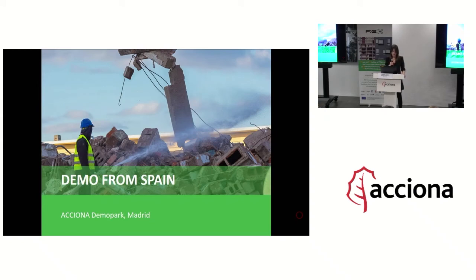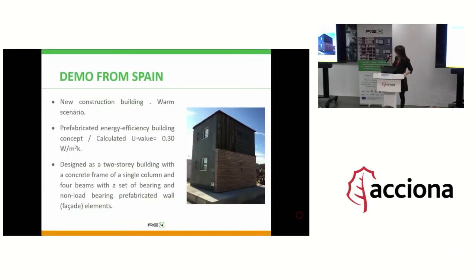Starting from the demo from Spain, this demo is the one we will visit later on. Here you can see the demo building. This building is built with prefabricated components. All the facade elements are designed to have a U value of 0.30 watts per square meter Kelvin, which is much lower than the U value required by the Spanish legislation, which is 0.66 watts per square meter Kelvin. And this building has been designed as a two-story building with a concrete frame of a single column and beams with a set of bearing and non-bearing prefabricated wall elements.